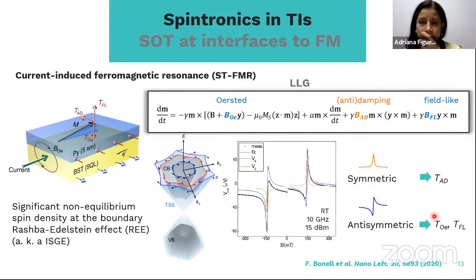This is also related to what Rafael was asking about. The Ørsted-like torque is the one that is just due to the current flowing through the sample, and the field-like torque is the one that, as you said, is also perpendicular to the magnetization. You have these two kinds of contributions that are part of the antisymmetric component of the FMR. This is the one we're interested in, because it is related to the spin accumulation at the interface. I see.